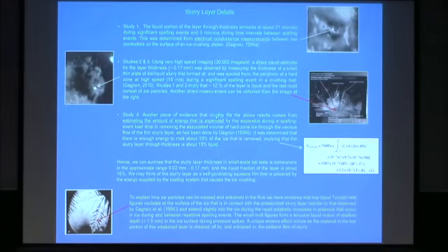Now, don't worry, you don't need to read all this. Basically, it's referencing a number of experiments that were used to get some information about this slurry layer. The slurry layer is so important. So we had the liquid sensing experiments here. We also had the case where we could measure some ejecta from the hard zone and get some edge-on measurements of thickness from that. We also had a measurement from the thick section crushing, where we could view the thickness of the layer, get a measurement there, and those values were consistent.